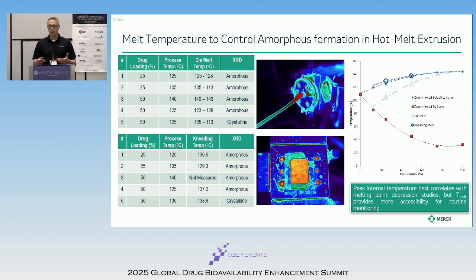What you're going to see, though, when you actually open the extruder, and in this case we used an IR camera to measure local temperature, is that there's actually a much better correlation, suggesting that there is a strong dependency on that internal temperature in terms of being able to generate your amorphous system. And it also really illustrates the fact that you will have local temperature elevation during the extrusion process internal to that system.